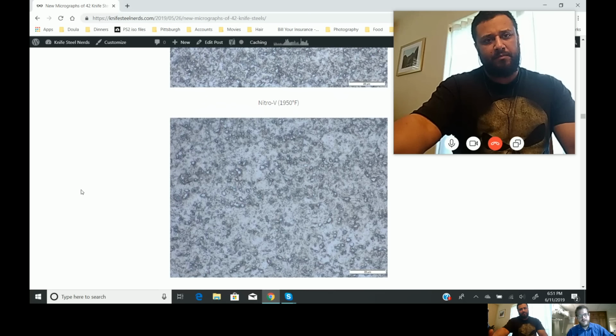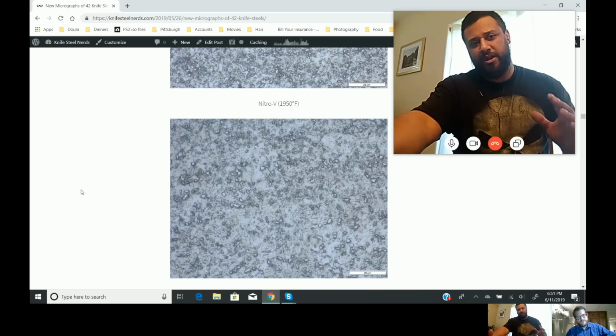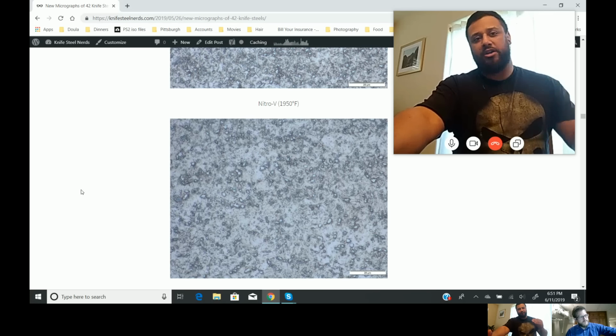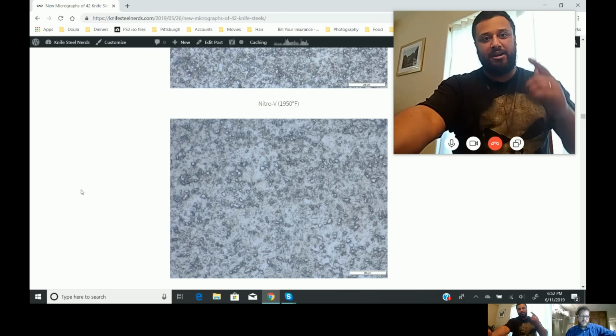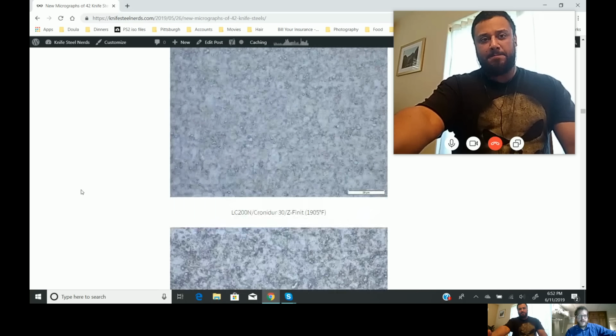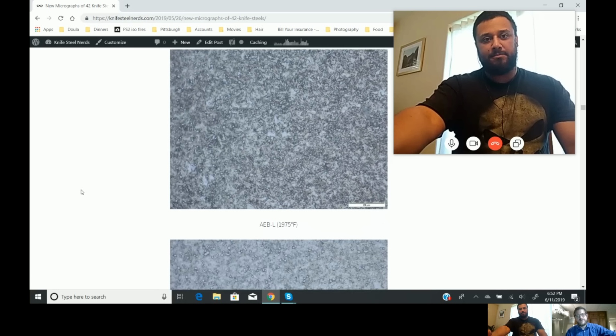I don't really know. Now, just real quick, we've got to take a pause here because people are probably looking at these micrographs and they're like, okay, those are the finest, so those are the best. But it doesn't always come to that, right? As far as wear resistance is concerned, and that's a component of edge holding. These finer carbide steels, while they're nice for one aspect of edge holding, as far as testing on CATRA and things like that, these steels don't do very good, huh? Yeah, these four we just looked at, they have very poor wear resistance.